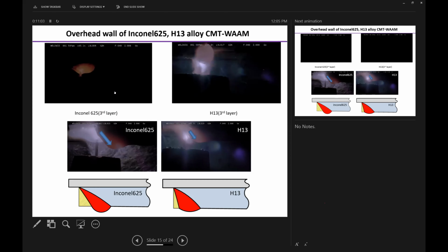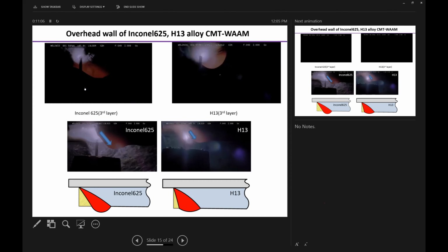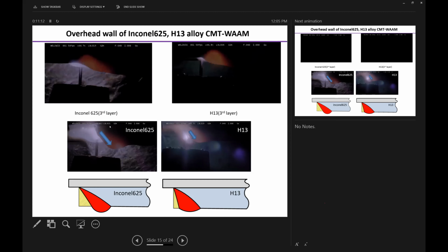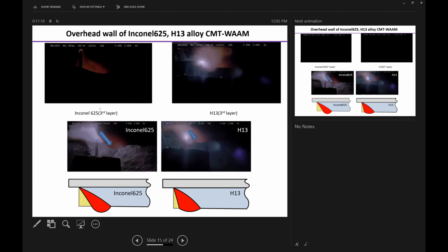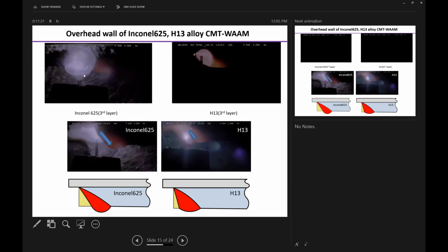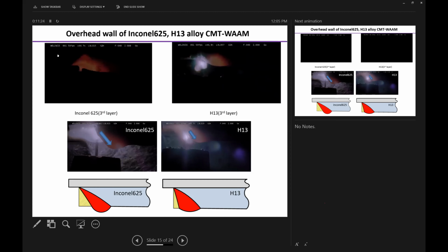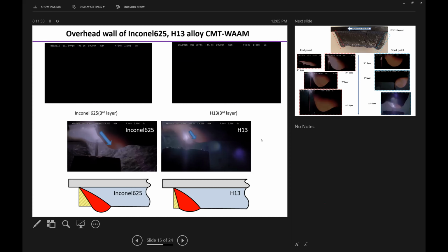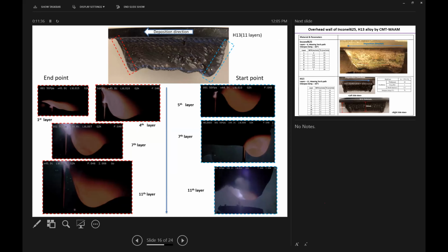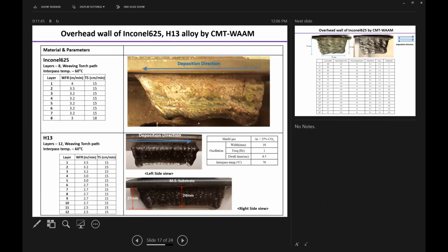Yeah. So we observed the process by recording the video during the welding. It was observed that for Inconel material, the amount of molten metal during the deposition was higher as compared to the H13 alloy, and due to that, the Inconel had more reduced length at the end. So these are the images which show how this issue accumulates layer by layer.